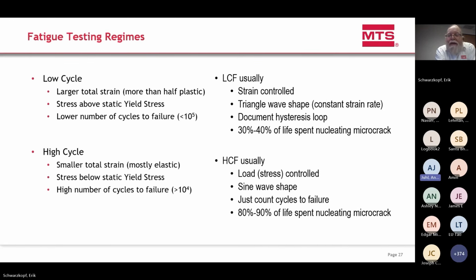HCF usually has a high number of cycles to failure. And if we're trying to get the test done in a reasonable amount of time, that usually means you're running at a higher frequency. HCF is usually stress oriented and with a sine wave shape. And the information that's most important in an HCF test is probably the cycles to failure.